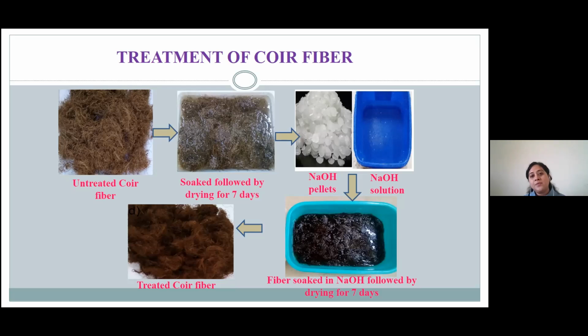Initially, these fibers were immersed in water for 7 days. Then they were again dried for 7 days at room temperature, so that we ensured that the waxy substances and natural oil are all extracted.